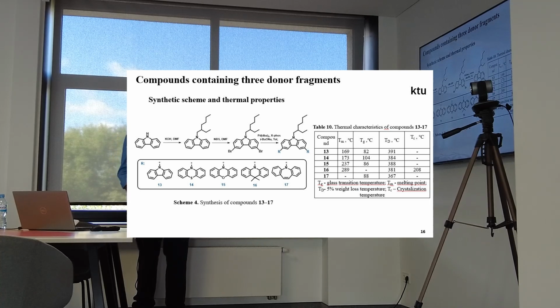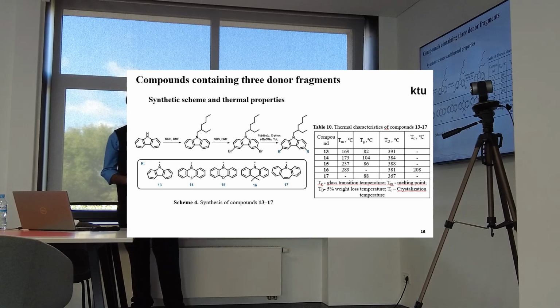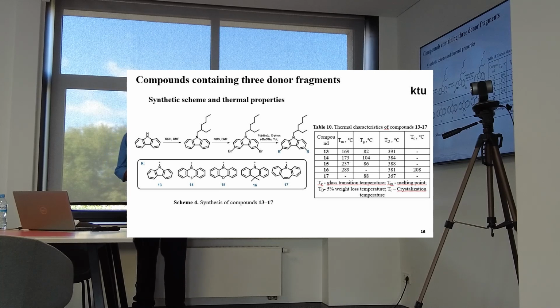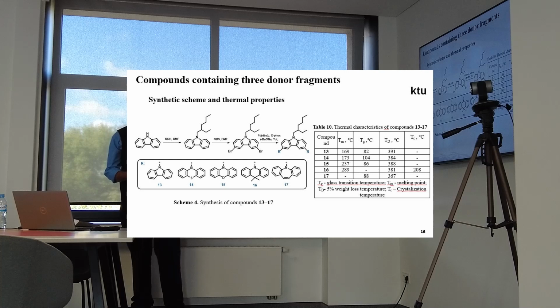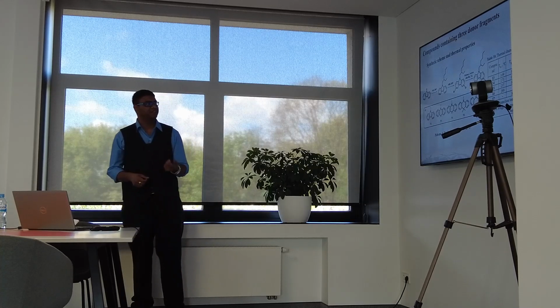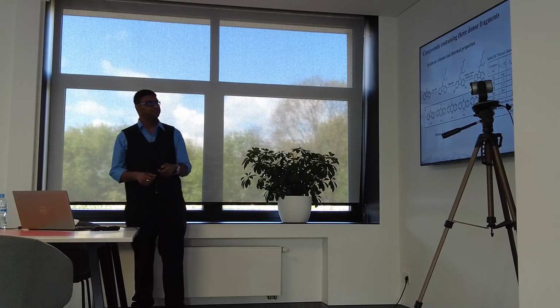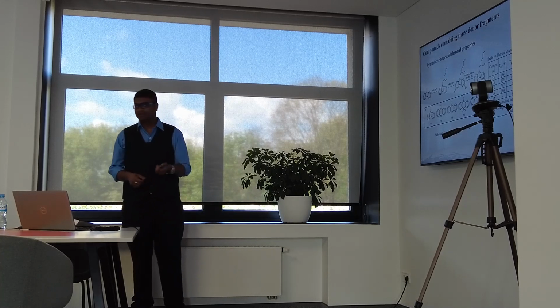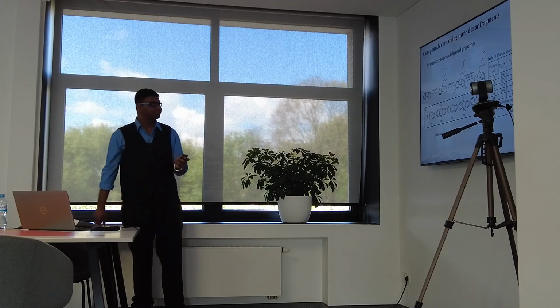and the target materials were synthesized in a multi-step reaction, and in the last step Buchwald-Hartwig was used to synthesize the target materials, and the thermal properties revealed that the weight loss temperature or TD in the range of 367 to 391 degrees Celsius, and the differential scanning calorimetric analysis revealed that compounds 13 to 16 are crystalline in nature, and compound 17 is amorphous in nature with 88 degrees Celsius of glass transition temperature.